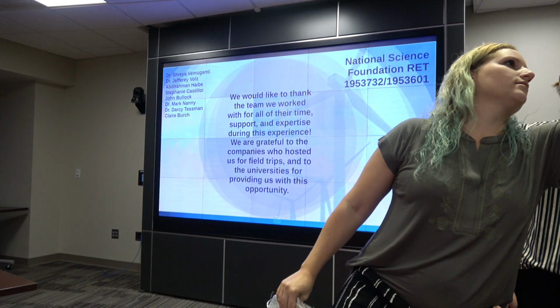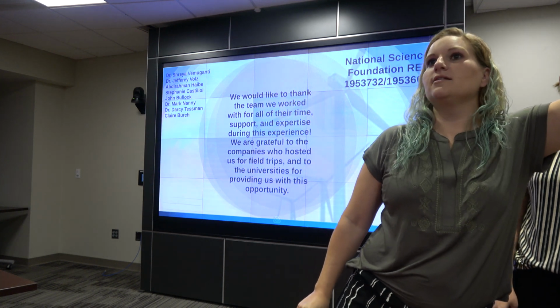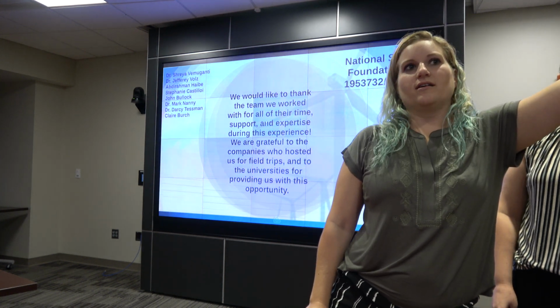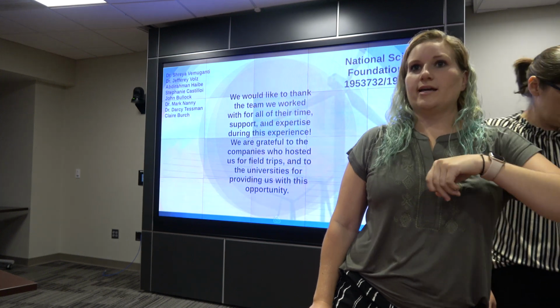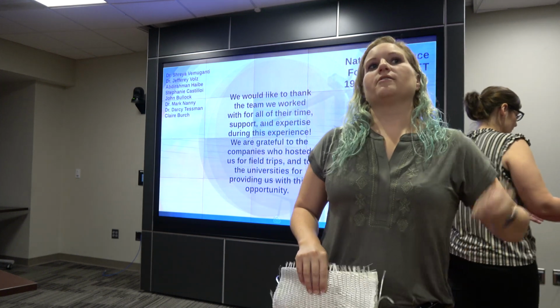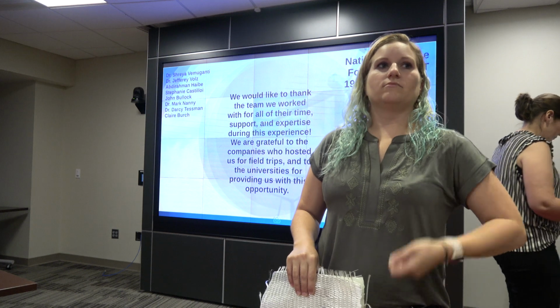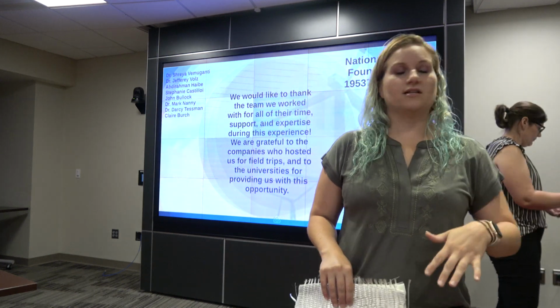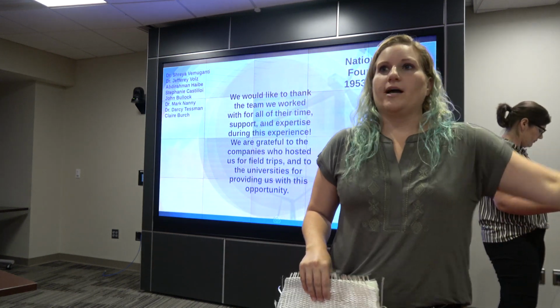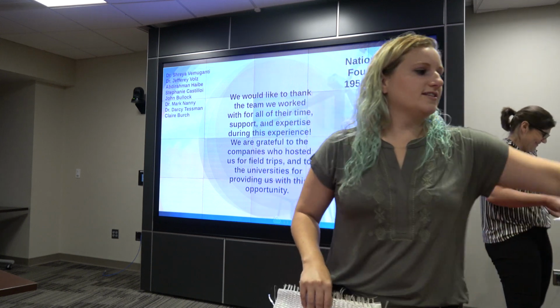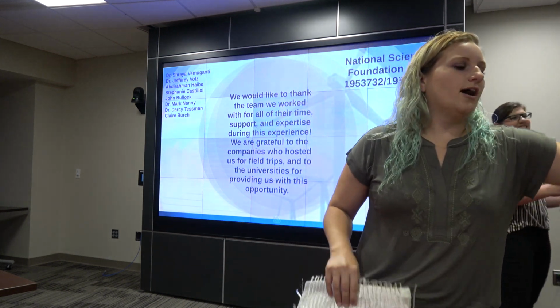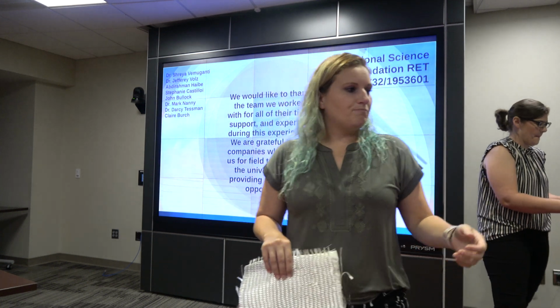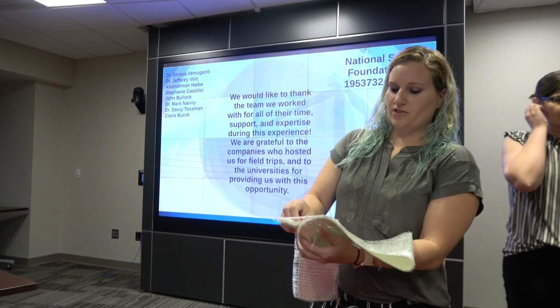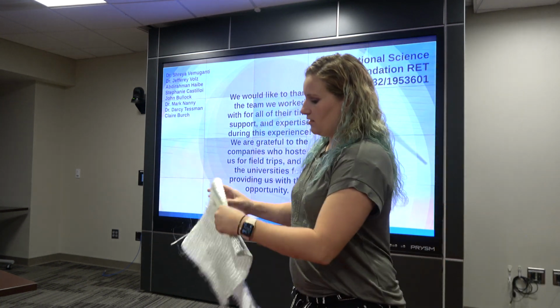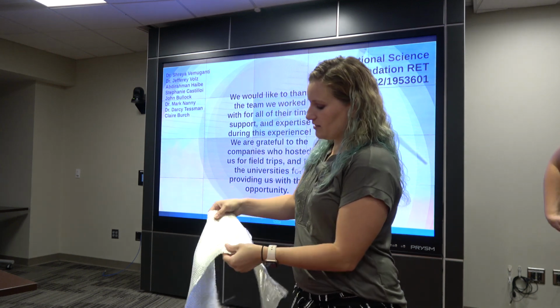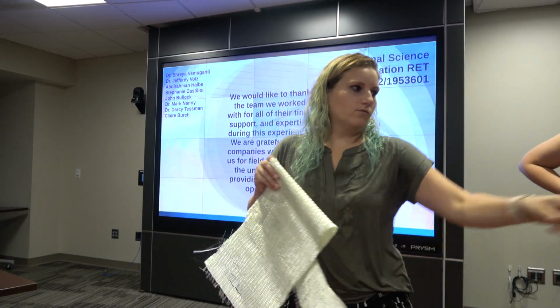You can almost see more of the glass fibers. This one didn't end up as saturated with the epoxy resin when we were laying it up, because once we do layers, each layer you had to put a layer of the epoxy resin, and we did that several times. And then this one we were like, no, just keep pouring, keep pouring, keep pouring. So these actually became so saturated, we could barely bend it. But luckily, with the way that these are, it's a lot harder, obviously, to bend this way than it was to bend it this way once it was hard enough.